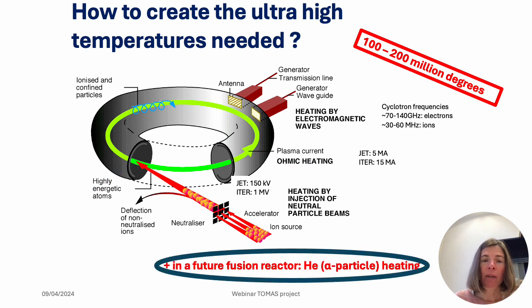Lastly, when you realize your fusion reactor, you have a bonus heating. The bonus heating comes from the helium. It is a charged particle, it's produced in the reaction, and it carries 20%, 3.5 mega electron volt, 20% of the energy, and it is charged, so it will stay in your plasma, and it's a way to keep the fire burning. But this only happens once you have already realized your fusion reaction.